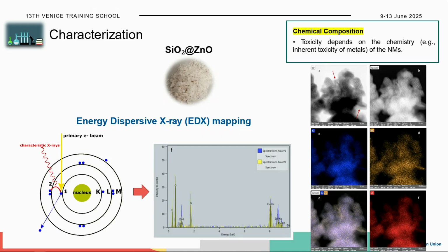So we move on. We also characterized the material by looking at the chemical composition in this case. So we would like to understand how we can understand if this is actually coated or not by zinc oxide. So we use EDX, in which we can observe different mappings of the different elements. So this is, I would say, a qualitative technique. It's not quantitative, but can give us an idea about the elemental composition of the material. So we compare the map of the zinc on the sample, and then the silicon here, and then we merge the 2 maps. We observe that there was a kind of agreement of these two maps on top of each other. So we can say that this material is actually composed by silica and then, I would say, a layer, not nanoparticles, of zinc oxide.